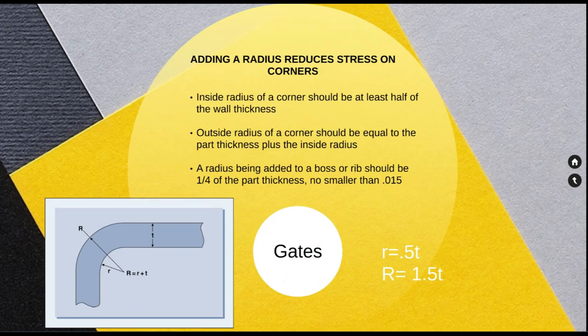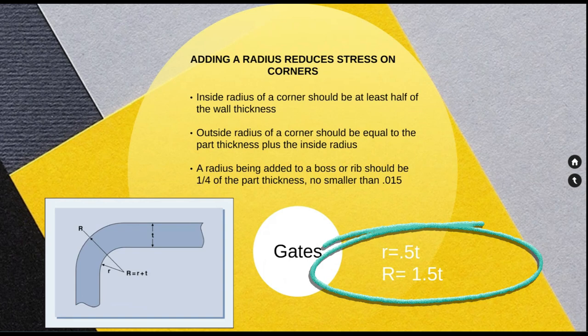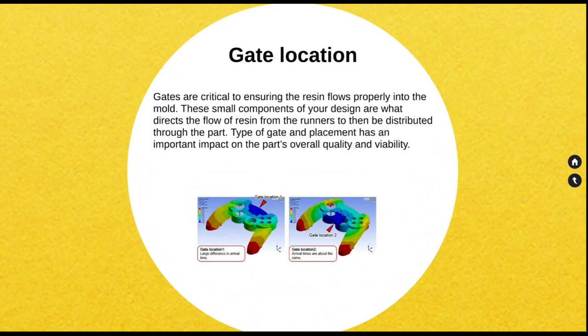Let us see some other parameters to be considered when designing plastics. Two things covered here are giving the right radius on corners and choosing the gate at the right location. The inside radius of the corner should be at least half of the wall thickness, and the outside radius of the corner should be equal to the part thickness plus the inside radius — so the outside radius R equals 1.5 times the thickness of the part.